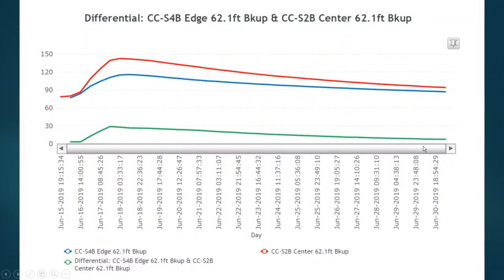This is a graph from our software that shows the in-place temperatures. The red line represents the center temperature history. The blue line represents the edge temperature history, and the green line down here represents the delta between them. So you can see that we had a peak delta of just under 30 degrees, and then that nice smooth lowering of the delta over time. This is almost an ideal mass concrete temperature graph.